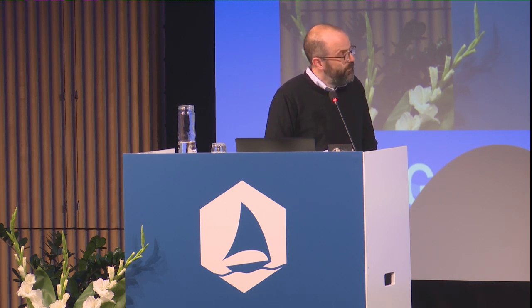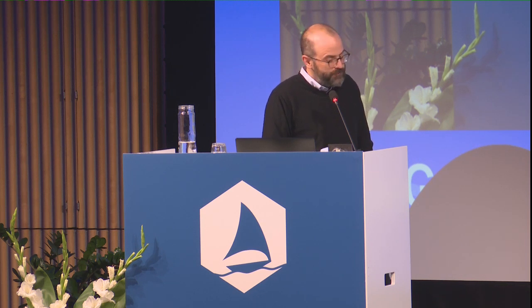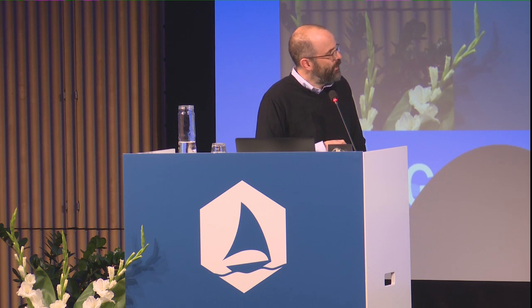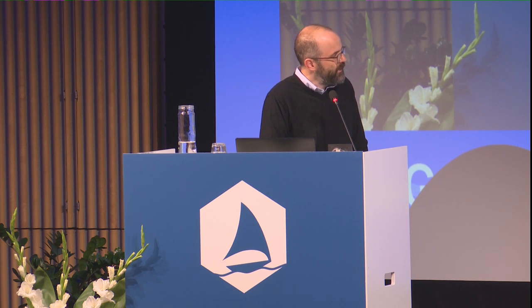So that takes me to the next part of my talk, which is that we can modify the interlayer separation between these materials by squeezing. And again, this is because of the weak van der Waals interlayer forces. So how do we do this? This experiment we reported last year, what we do is imagine that we can take this device structure, put it into a pressure cell, fill the cell with oil, press on the cylinder, and squeeze the layers. What we can do is basically drive up, we think, the interaction between the graphene and the BN by decreasing the distance between these interfaces.